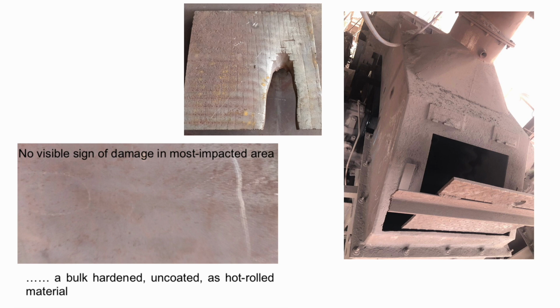Now, we replaced that with our steel, and this was before the pandemic, and it was examined just after the pandemic, and there is no visible sign of damage. So that's over a period of years, and even now I haven't heard of any damage on this. So by replacing the hard-facing steel with the new steel, we save an enormous amount of CO2. And that should be the ultimate goal of developing completely new steels, is to reduce CO2 production by using less steel.